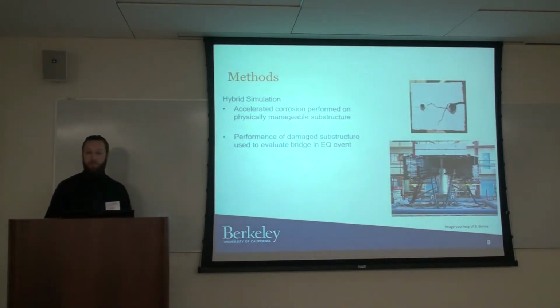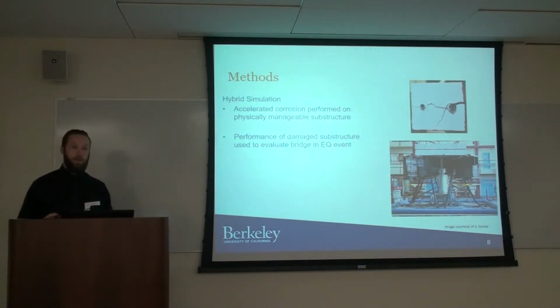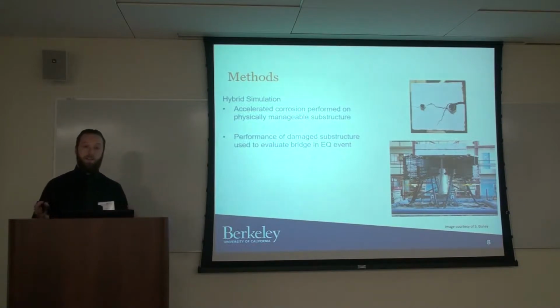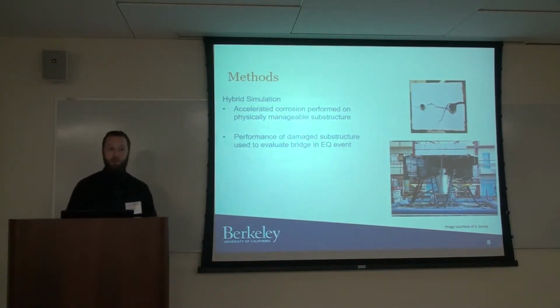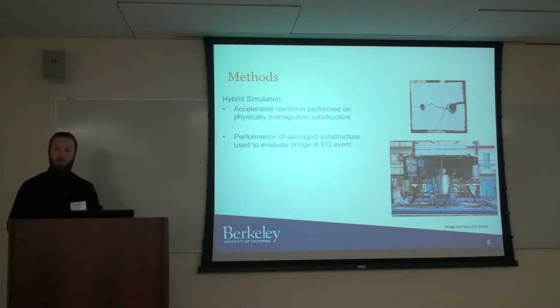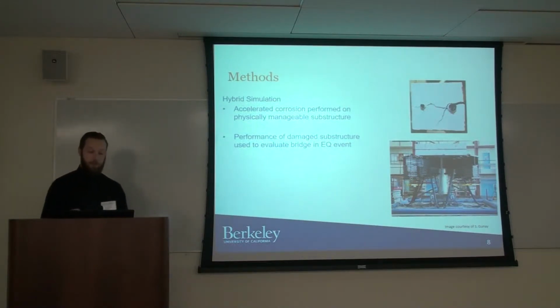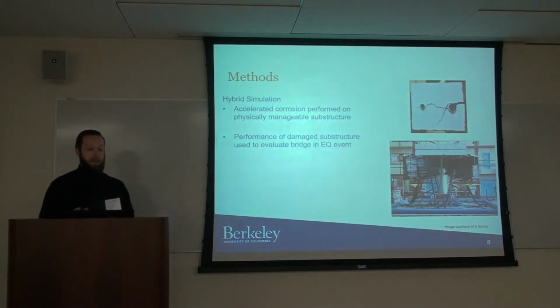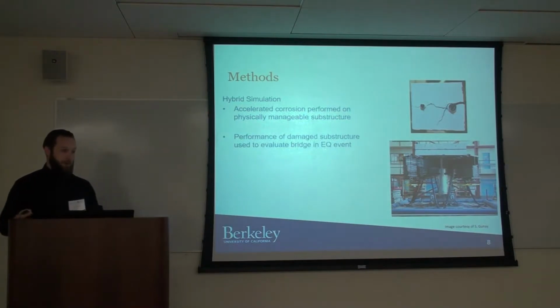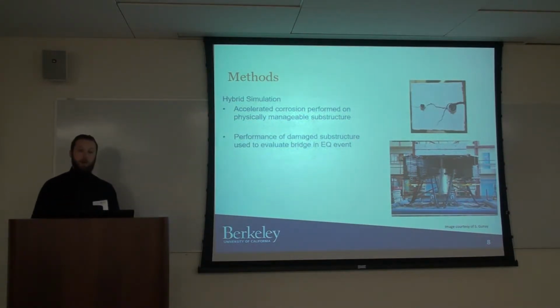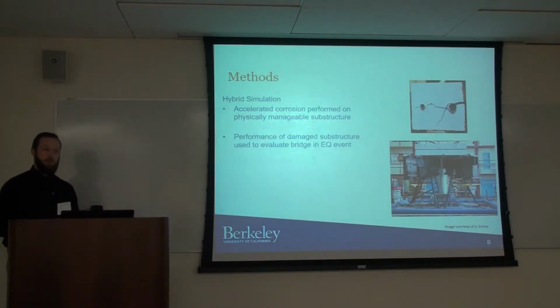And so in this experiment, we're considering accelerated corrosion on a physically manageable substructure, specifically just the plastic hinge region of a bridge structure. And then after inducing corrosion on a specimen, we can use hybrid simulation to determine the influence of damage in this region on the overall performance of the bridge.